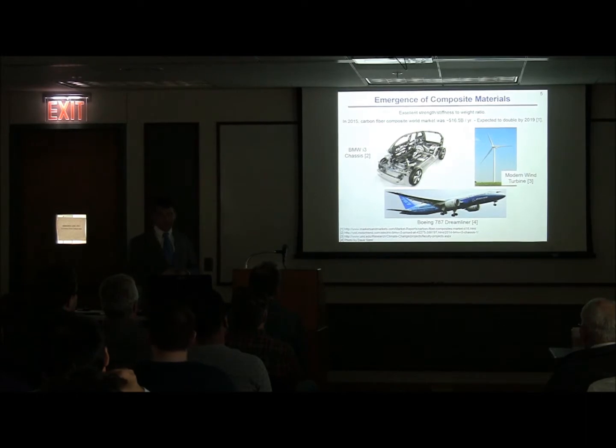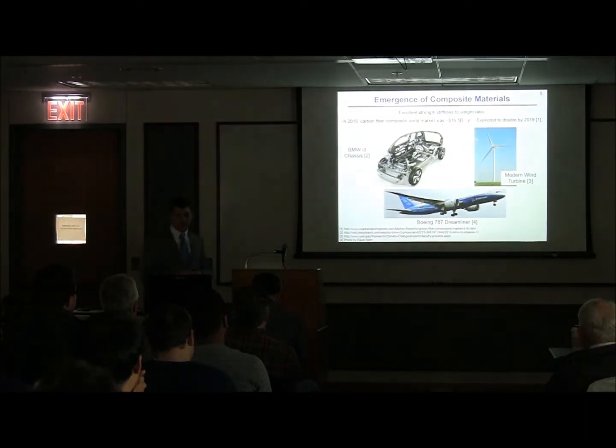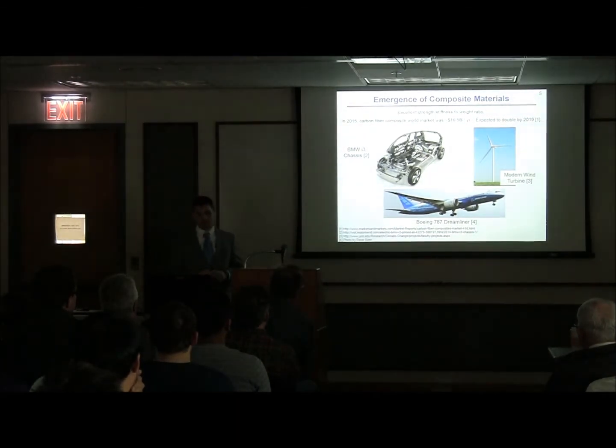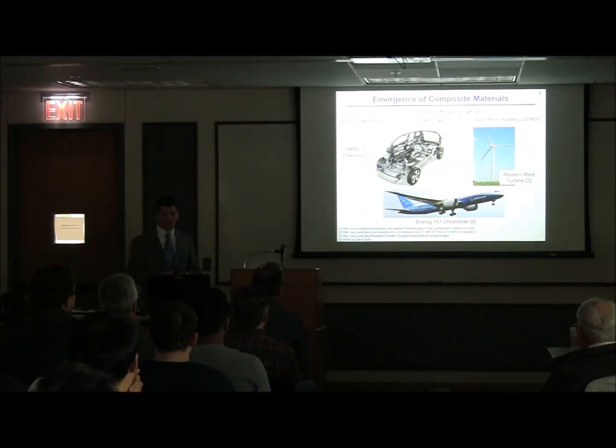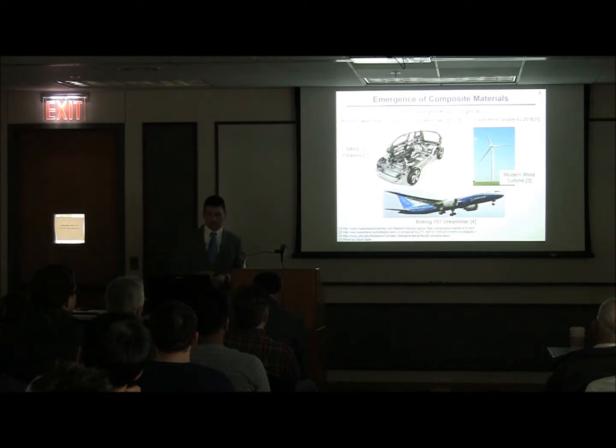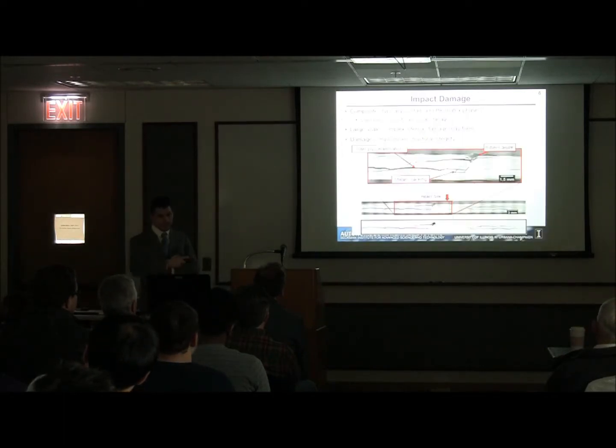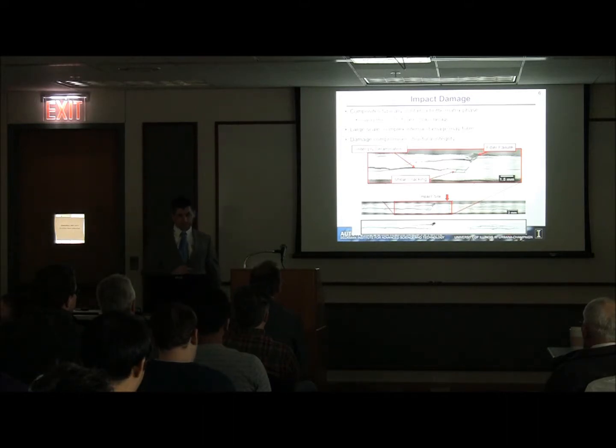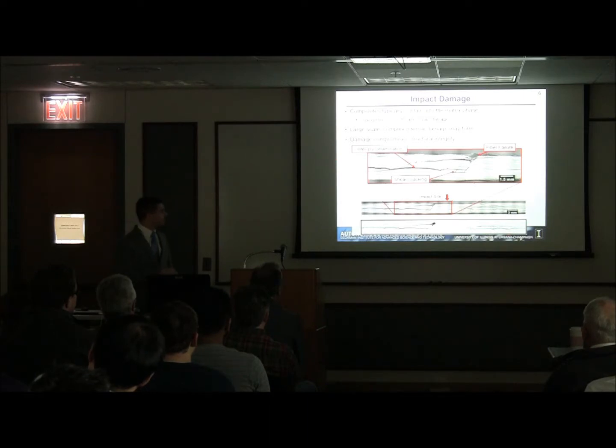So to give you an idea of how fast these materials are growing, in 2015, the carbon fiber composite world market was valued at $16.5 billion a year, and that's expected to double by 2019. So that's a tremendous growth rate for these particular materials. But they're not without their disadvantages. One of the disadvantages of composite materials is they're typically made with a brittle matrix phase. That brittle matrix phase leaves them susceptible to out-of-plane impact damage and can cause damage inside of the material that is large scale and complex. It can compromise the structural integrity of the part.